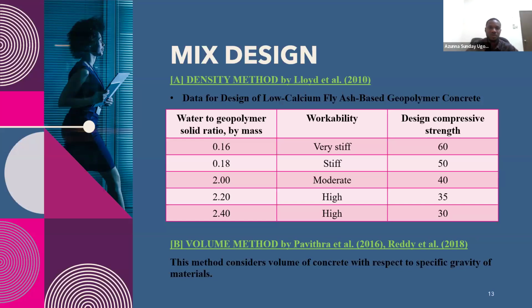So I'm currently doing my geopolymer concrete in the lab, and I used both of them. If you use the density method, you're going to have a lot of challenges because it assumed 2,400 kilograms per meter cube for its design. But in reality, achieving 2,400 as density of concrete, most times it's not achievable. So if you use it for your design, you see that there is quite an unbalance in your mix ratios.